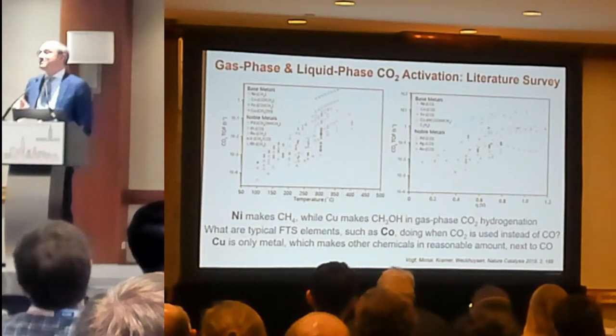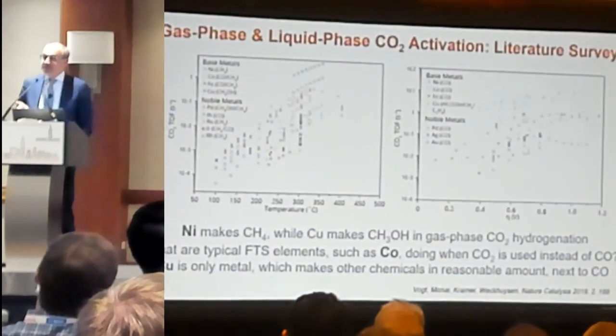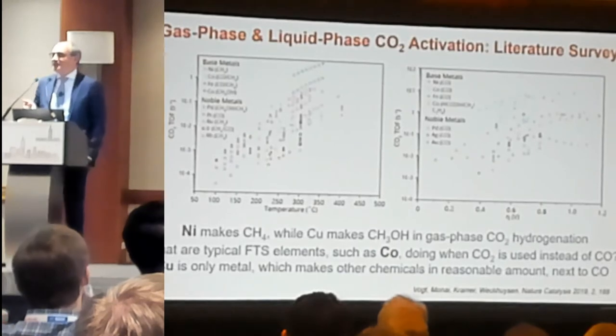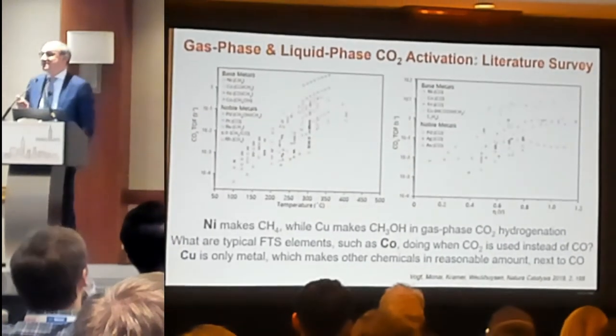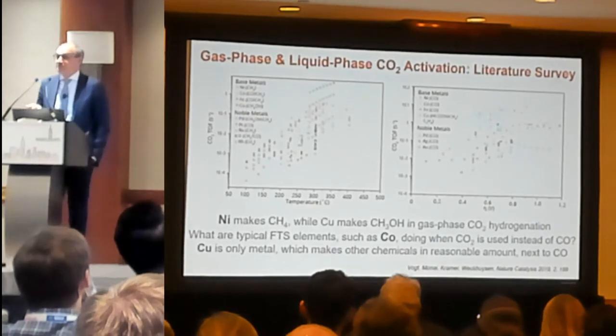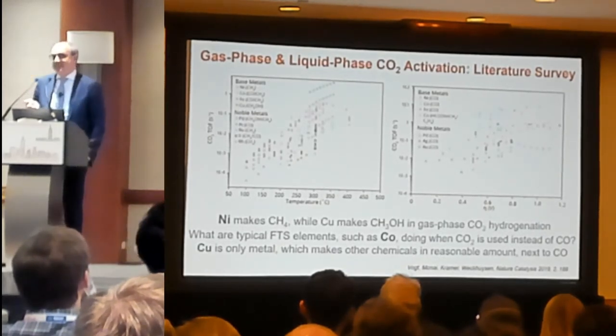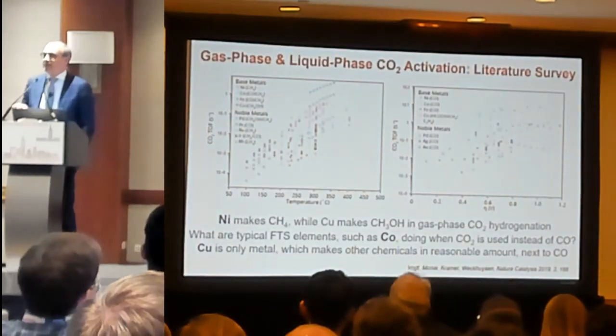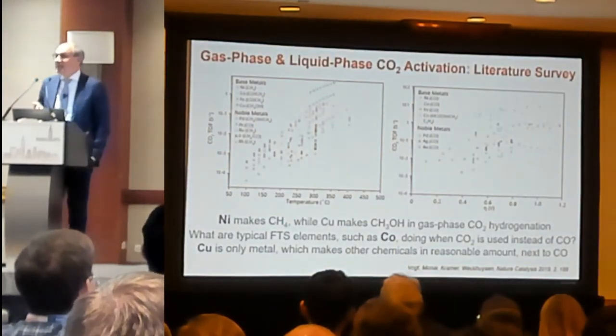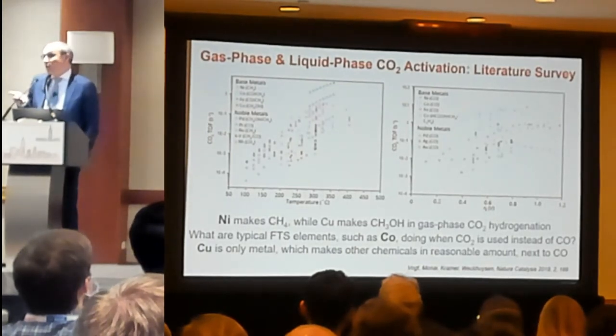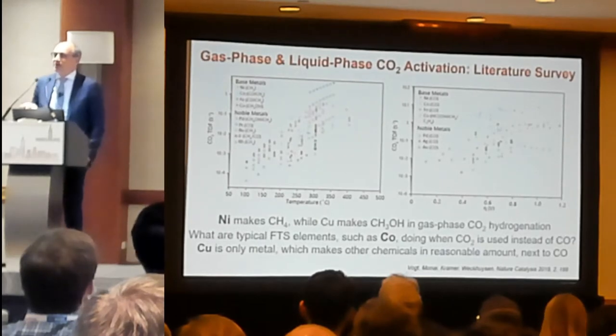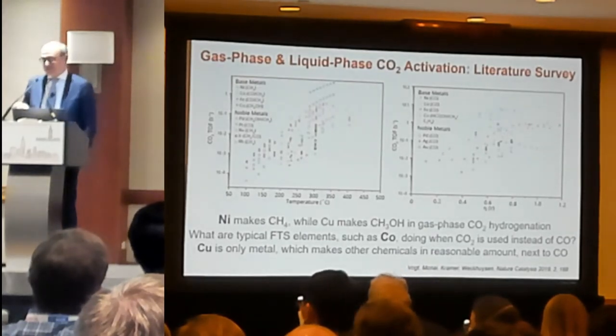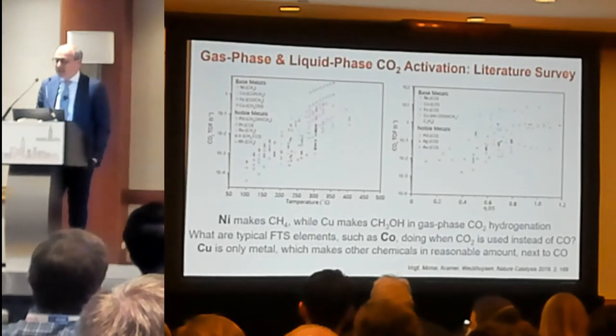Here I show you a literature survey. On the left you have gas phase, and on the right you see electrocatalysis of CO2. It compares the different base and noble metals for doing this reaction. It's very peculiar to see that with cobalt you can make long-chain hydrocarbons and with nickel mainly methane for gas phase CO2 hydrogenation. With electrocatalysis it's also interesting that you can make CO and methane, but also C2 coupling products with copper.